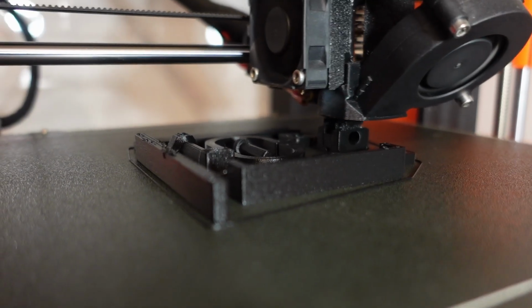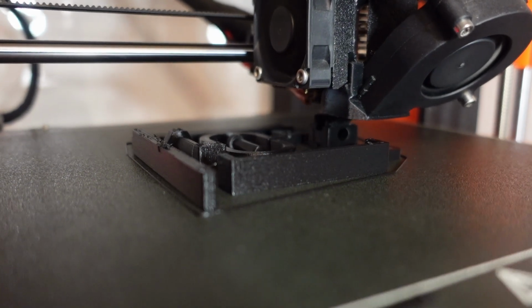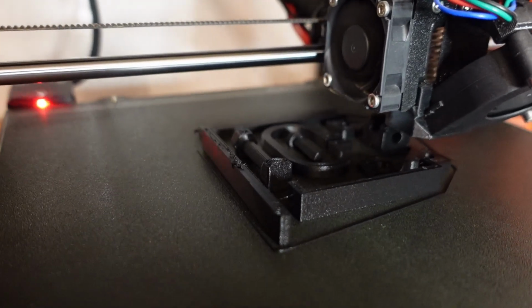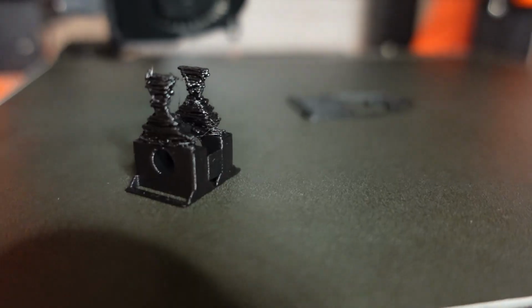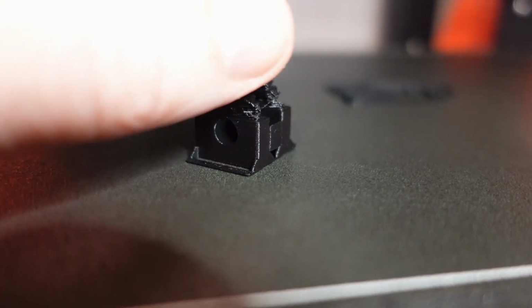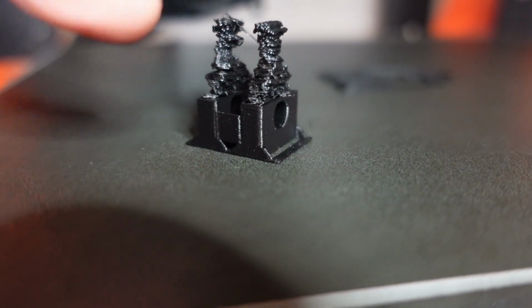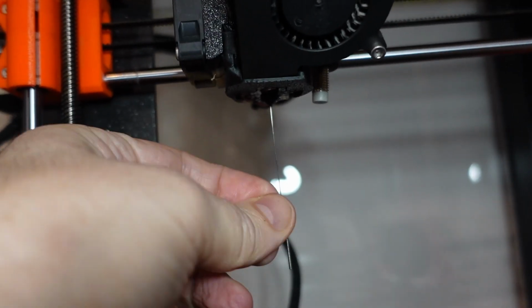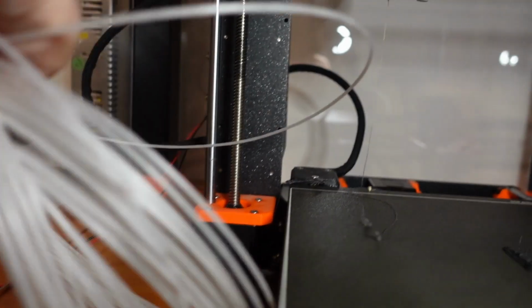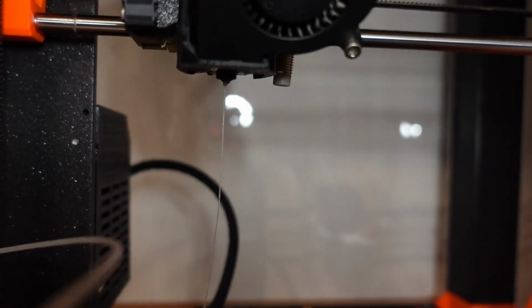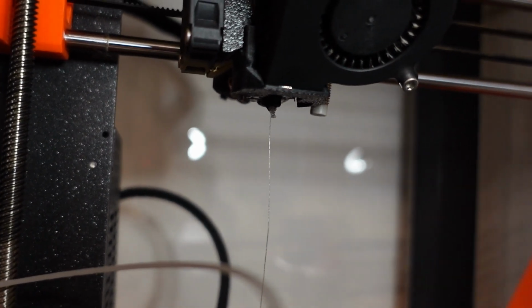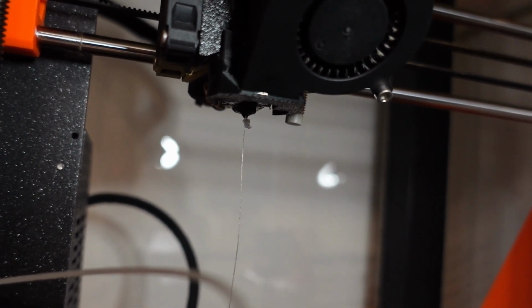And here actually the problem started. I didn't notice immediately, because after approximately 10 millimeters, when all test objects were printed except these two, I had a clog in the nozzle. I tried to clean it using the needle, even some cleaning filament, cold pull, but I ended by replacing the steel nozzle with the brass one.